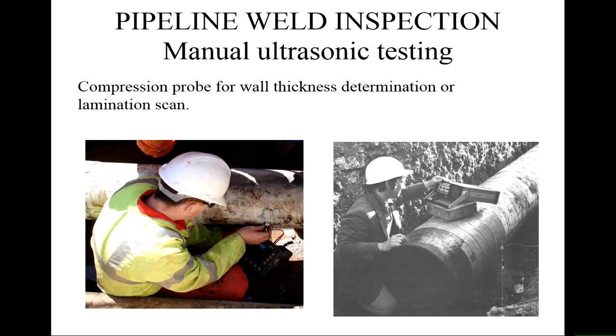And it can work on site. It's very widely used for looking at lamination defects, which have been introduced during the rolling process. So if you put the probe on the surface, a 90-degree probe, you scan the sound down, it bounces off the back face and then comes back up, that's good. If it scans down and finds a lamination halfway through, you measure effectively half the thickness of the pipe, or whatever. And at that point you can reject the pipe.